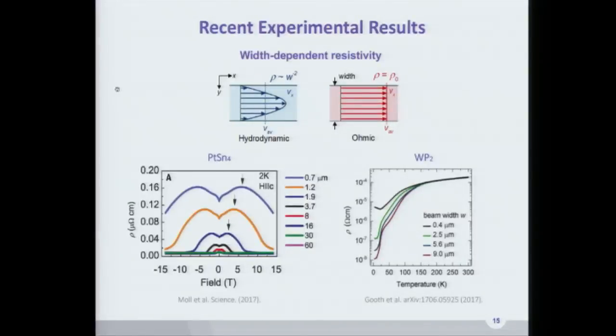So that's where I got interested, and I said, okay, so you'd expect this with dependent resistivity. But another thing that's surprising to us about hydrodynamics is that most people were using models that treated the lifetimes as something very approximate, and then from there backing out these very complex expressions. We wanted to go microscopics first, where we think about the microscopics in great detail and see if similar viscosity expressions fall out of it, right? So instead of starting with the hydrodynamic picture and imposing it on the material, start with the material picture and see if you recover the hydrodynamics. Does that make sense? Okay.